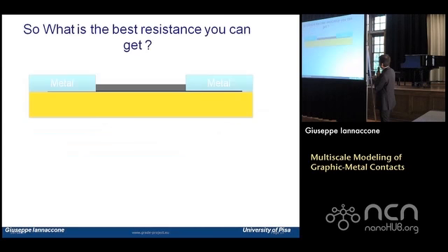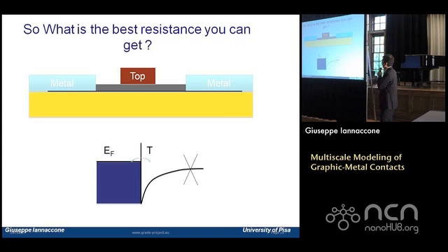Because, for example, what can we do if we need to fabricate a GFET? We have this yellow region, which is an insulating layer, then we put a graphene layer on top, two metal regions, and a top dielectric. Then we put a top gate, and the figure below shows what happens at the contact. We have the metal region, the Dirac point at the interface with the contact, and then the energy of the Dirac point in the space of less than 1 nanometer goes much closer to the Fermi energy.